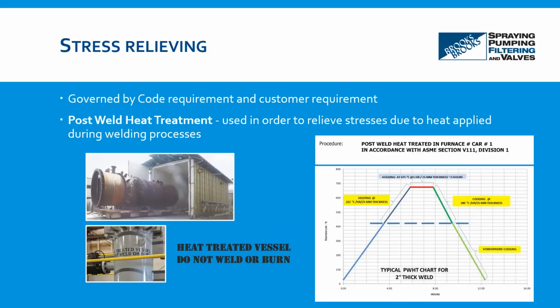Another one is the requirement provided in UCS-56, when your nominal thickness exceeds a value of like 1.5 inch for carbon steel material. UCS-56 also provides the minimum post-weld heat treatment temperature and the holding time based on your P number and thickness of the material. Finally, UCS-68 also, when your minimum design metal temperature is below -55°F, you need to do mandatory post-weld heat treatment based on the requirement or even the procedure given in UW-40 of ASME Section 8 Division 1.